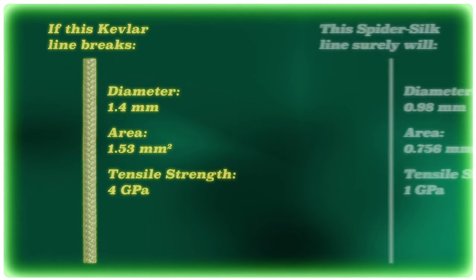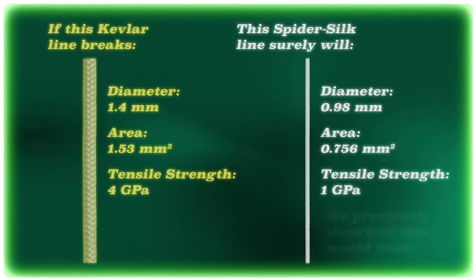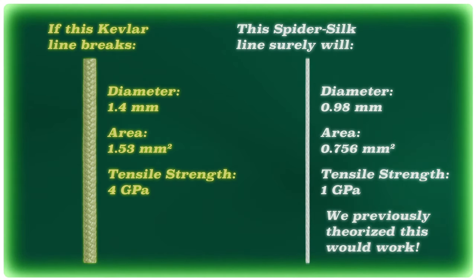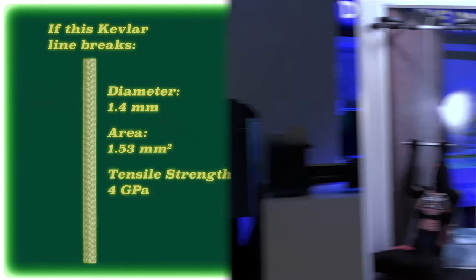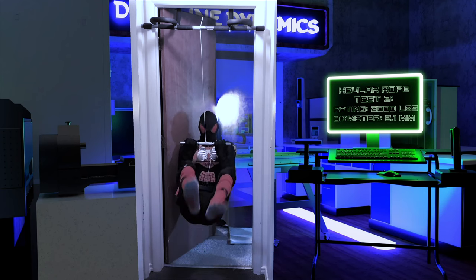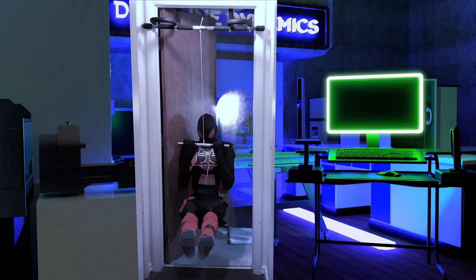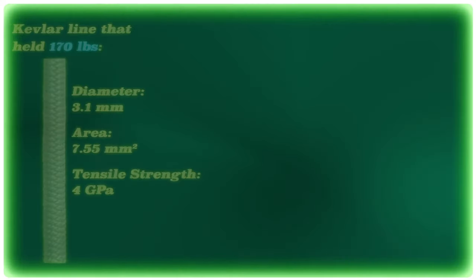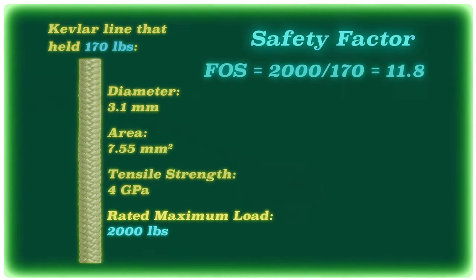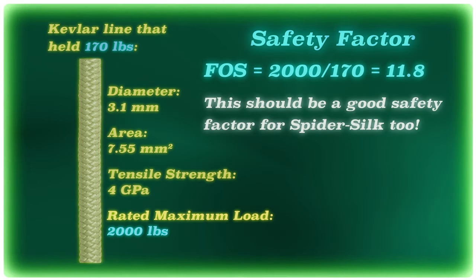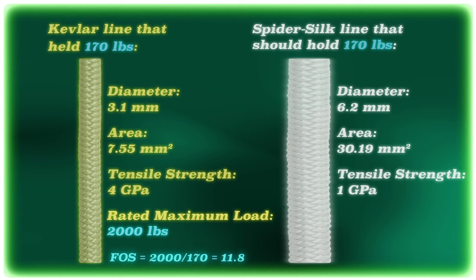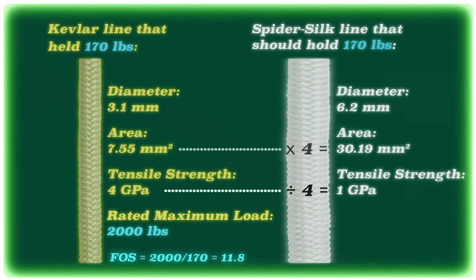so it stands to reason that the smaller area of 0.756 square millimeters for the weaker spider silk wouldn't come close. Now this Kevlar line, rated for 2,000 pounds and having a diameter of 3.1 millimeters, so a cross-sectional area of about 7.55 square millimeters, can hold my weight quite securely. Now this safety factor is, in theory, 2,000 divided by 170, or about 11.8. To get this same safety factor for spider silk, you need to multiply the cross-sectional area of the Kevlar line by 4, or multiply the diameter by 2 to get 6.2 millimeters.